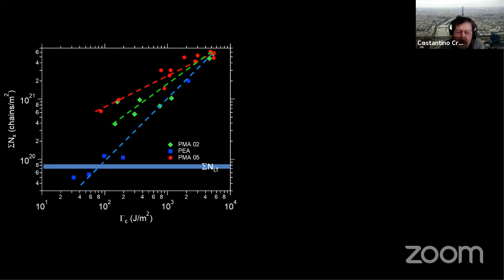Now let me try to summarize the data we have. In this graph, I show the energy that we expect to dissipate by bond scission. So this is sigma, the number of chains per unit area, times n, the length of the chain. So in a way, this is the energy that you expect to spend by breaking. The only thing that's missing is the energy per bond, the U_V, which we did not put in here. Now, if traditional models were correct, this should be a constant. So this band down here, sigma N L_T, is the prediction if we are constant.